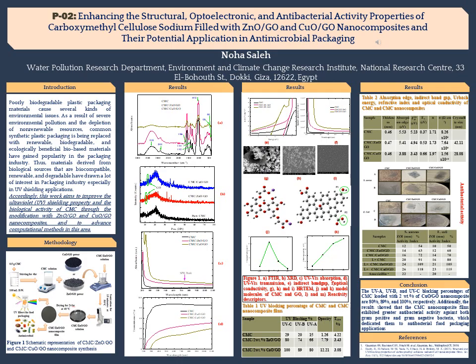Finally, the antibacterial activity of pure CMC, CMC, zinc oxide, graphene oxide, and CMC, copper oxide, graphene oxide nanocomposite films was evaluated against Staphylococcus aureus and Escherichia coli. The zones of inhibition data showed that CMC, zinc oxide, graphene oxide and CMC, copper oxide, graphene oxide exhibited higher antibacterial activity than CMC alone, particularly against Staphylococcus aureus.